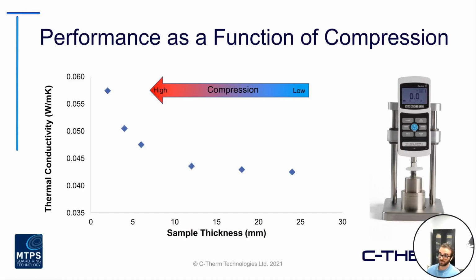Just as an example data set, you can see, similar to the result that I showed earlier based on effusivity, performance in conductivity can also be tested or mimicked as a function of compression. Again, this is another data set collected with the MTPS using the CTA, taking this compressible lofted sample. I believe this was an insulation type material. And it was applied or tested under different force loads. And looking here at the sample thickness being indicative of the force.